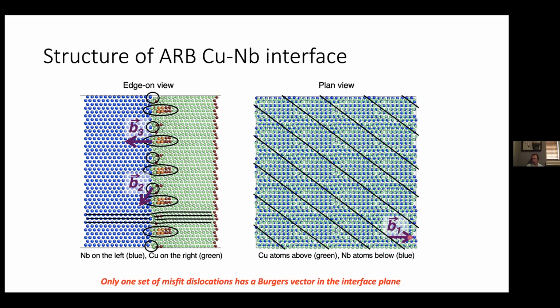This interface is going to be able to slip very easily in the direction of this Burgers vector. And in the perpendicular direction, it's not going to be able to slip very easily at all. So in other words, this one is going to have an extremely anisotropic shear resistance envelope, if you will, or a yield surface. And you can make that prediction based entirely on the dislocation-based structure of that interface.